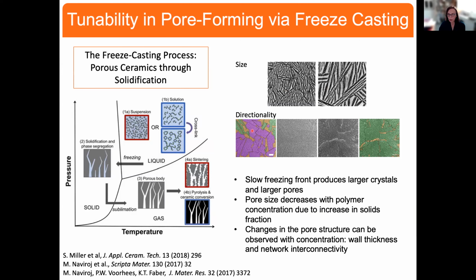So the takeaway message for this is that slow freezing produces larger crystals. The pore size also decreases if you put more polymer in there or more powder in there, due to that increase in the solid fraction. And we can also change the pore structure and wall thickness by templating with some degree of directionality.